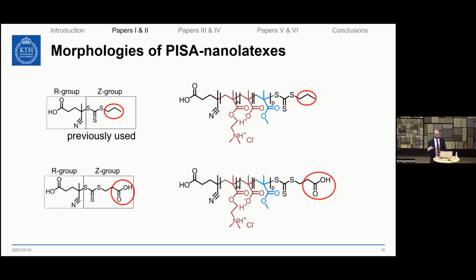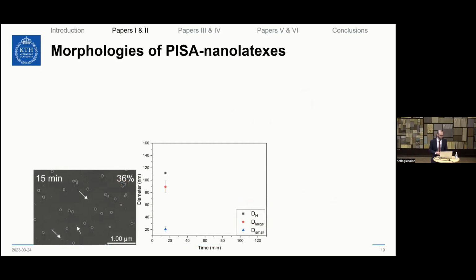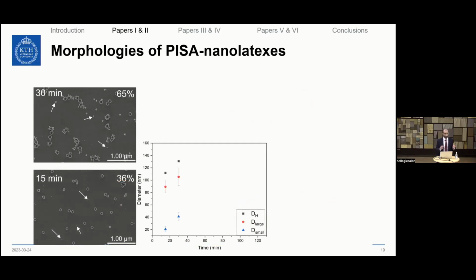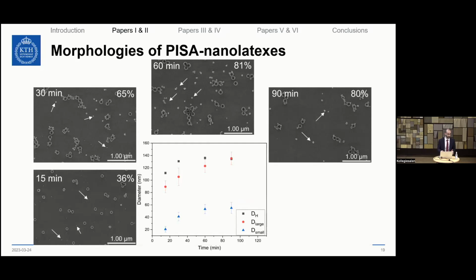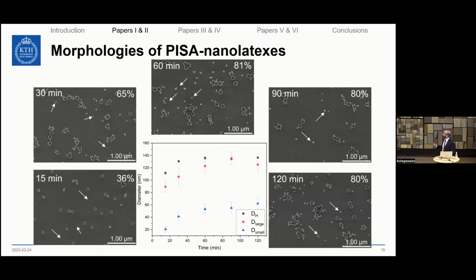However, when we prepare nanolatexes with exactly the same chemical composition, but with a Z group, which is a carboxylic acid instead of an aliphatic chain, then something very interesting happened. We saw that we could prepare bimodal reproducible nanolatexes. As you can see, we have two different populations. We have large and small nanolatexes coexisting at the same time, at different time intervals of the polymerization, and both populations increase in size until they reach a plateau, which also indicates the end of the polymerization.